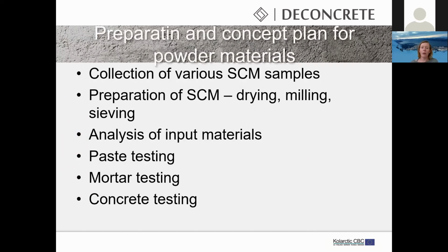All the powder materials used within this study were collected as a sludge. So the two types of sludge were collected in a very wet state. They were dried and milled, not with the purpose to reduce the particles, but to pulverize them because they were glued together by drying. And then all the types, including the fines from recycled concrete aggregates, were processed to obtain the same maximum particle size.